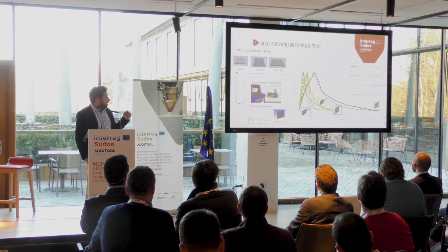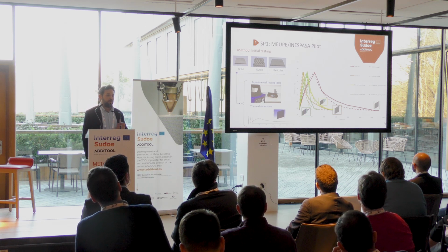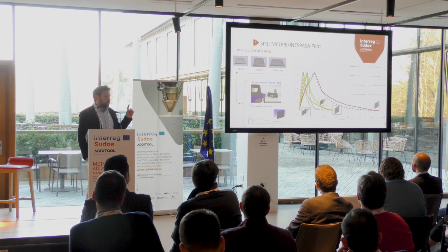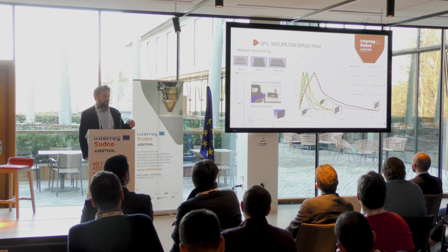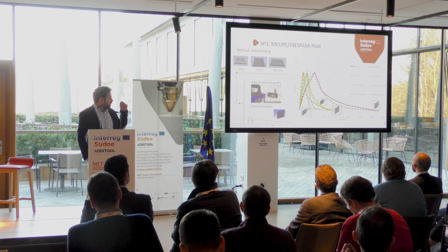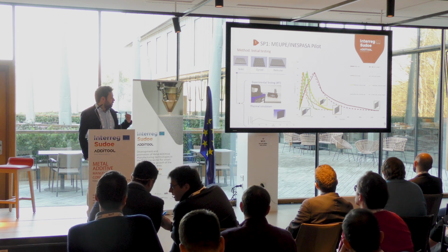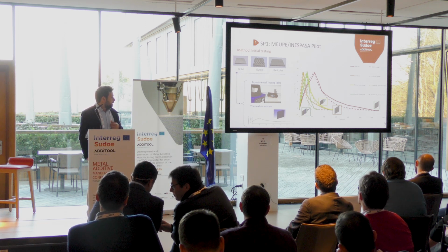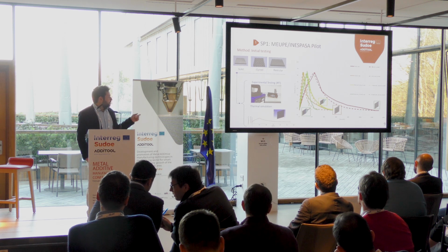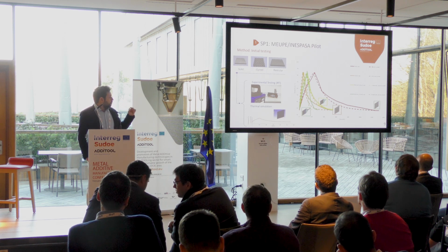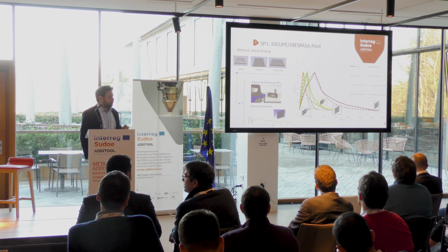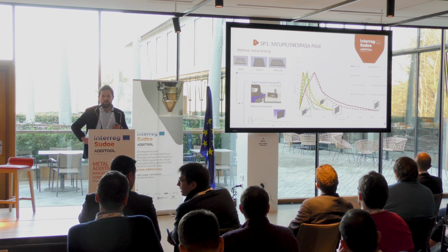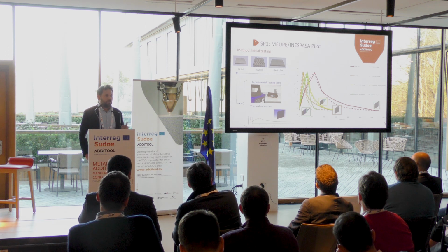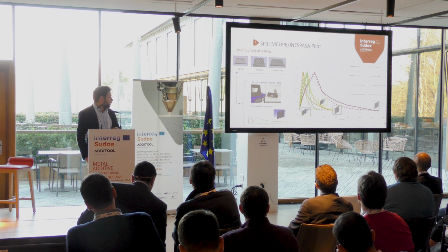And if you see the green one, once we put air on it during the cool down - we don't put air during warm-up to have the same condition - comparing the yellow with the green, we reduce the cool down process 2 times. And comparing the green with the red, we reach 85 degrees faster, but the cool down is decreased by 6 times, something like that.